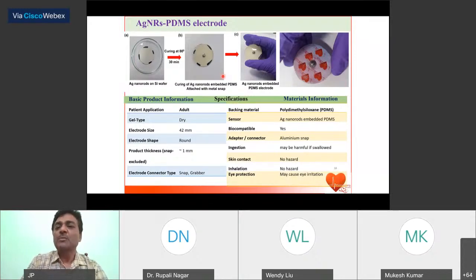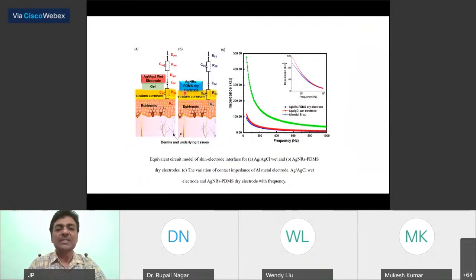But the best part is we have also made a wireless version. Here I'm comparing these electrodes with the conventional electrodes. You see, this is our skin, the outer side, which is stratum corneum, and then the outer epidermis. When you use the gel, the problem is that the gel solidifies over time, and the impedance changes, and the electrode-skin impedance increases, and then we won't be able to get the signal, because the signal is very small. It is of the order of a few millivolts. Because of high impedance, it gets dropped there. So we need a very low impedance here.